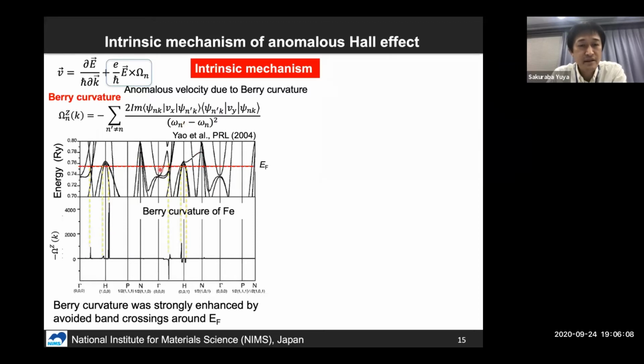As you can see in this example calculation for pure iron, the Berry curvature is strongly enhanced at the K point, where we can see several bands crossing at the Fermi level. So band crossing around the Fermi level is very important for the Berry curvature. And if we can calculate the Berry curvature, the intrinsic term of the anomalous Hall conductivity can be calculated by taking the integral of the Berry curvature in the full k-space under the Fermi level.